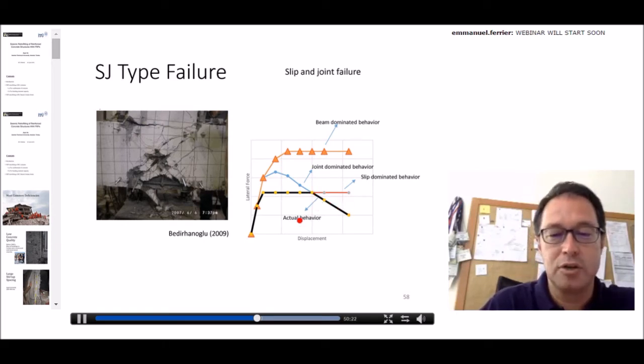So in total, we have this kind of partial ductile behavior and then a brittle failure, which is at a much lower load with respect to the beam-dominated behavior.